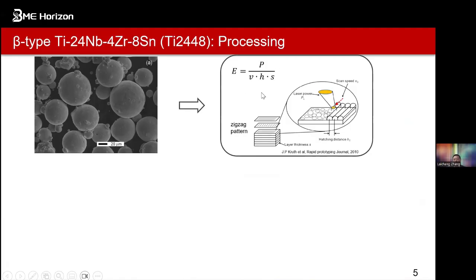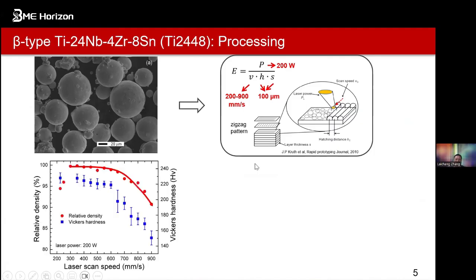We should use the parameters from processing. For example, the laser power, the velocity of the laser scan, the hatch spacing, and also the layer thickness. So those are the parameters. We use a zigzag pattern to produce 3D printed parts from the powders, for titanium cubes or structures. Of course, based on these things, we should know the relative density is very important to get high performance in mechanical properties and also corrosion resistance.